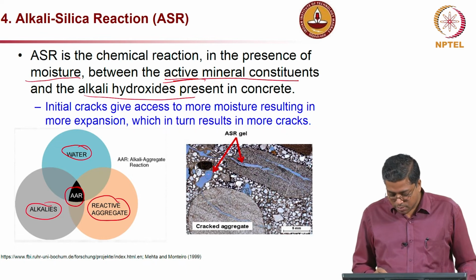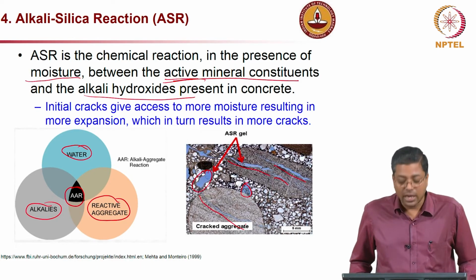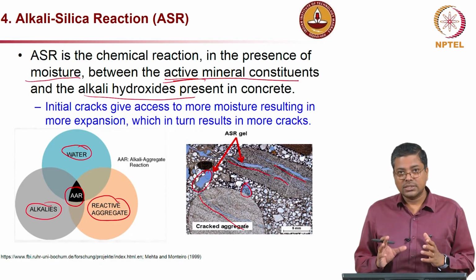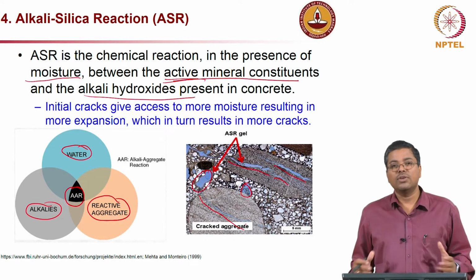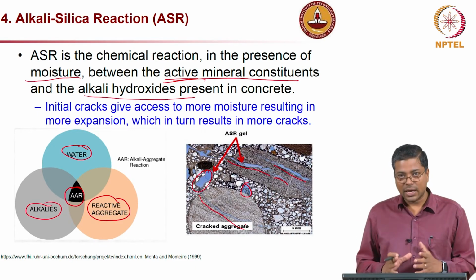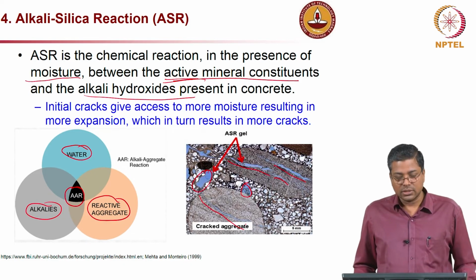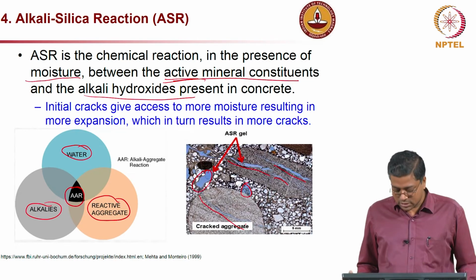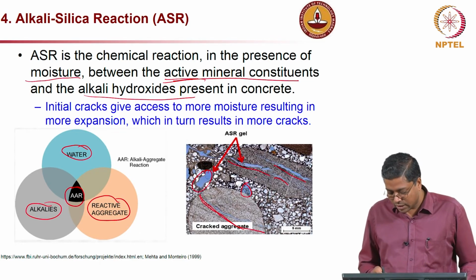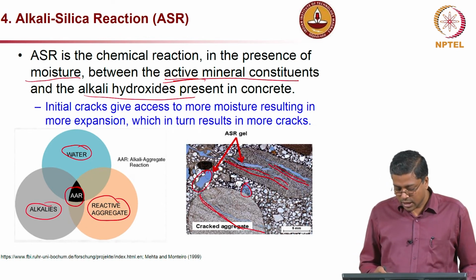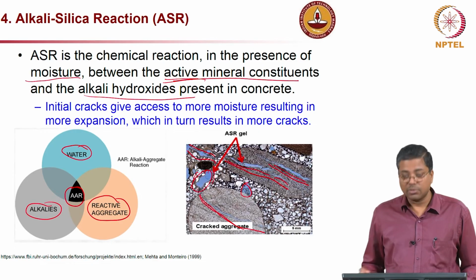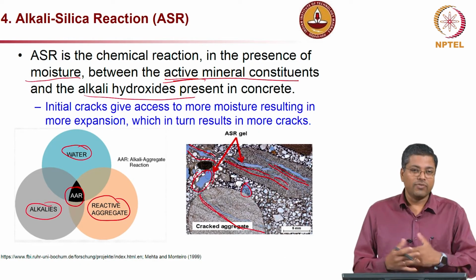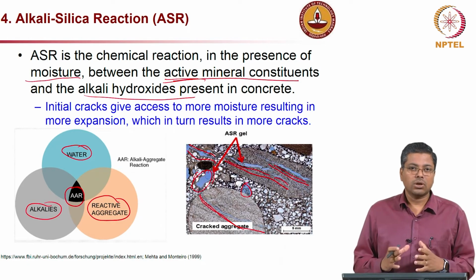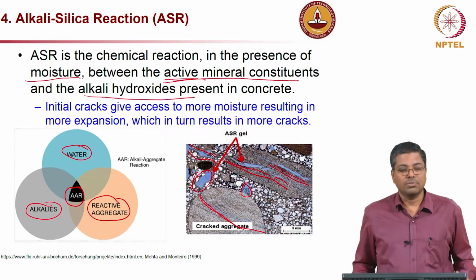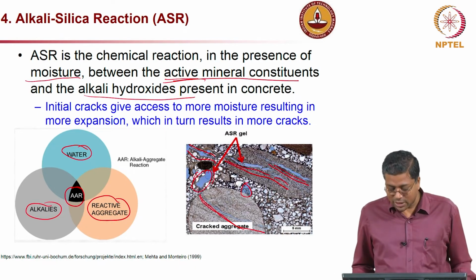The picture on the bottom right shows an example of how it looks. You can see all this blue colored region that indicates the gel, which we call ASR gel, and this gel induces significant pressure onto the concrete system. It is expansive in nature, which leads to an increase in the expansive stresses, and it can even crack the aggregate. You can see here an aggregate is cracked, and also significant cracking in the cement paste. Like we discussed in the sulphate attack, ASR also induces a lot of cracking of the concrete system, or the entire matrix gets damaged.